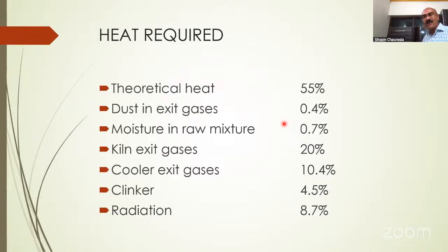That's the most modern kiln, and the efficiency has been hardly 55%, with all the equipment in the preheater and everything, and a lot of construction cost involved. If in a laboratory you synthesize the cement clinker, only 55% of the energy, heat, was required theoretically. The rest, 45%, was the loss. And what are those losses?